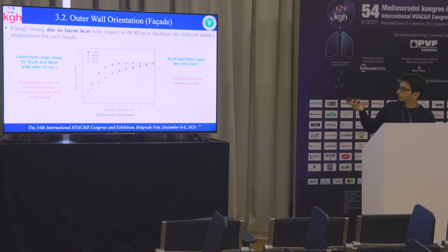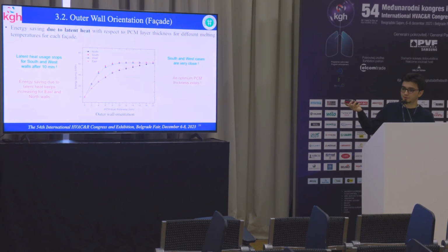And here also the energy saving due to latent heat utilization. As we can see here also, after 10 millimeters, the energy saving due to latent heat activation nearly stops. So after that, energy saving occurs only due to thermal resistance increase.